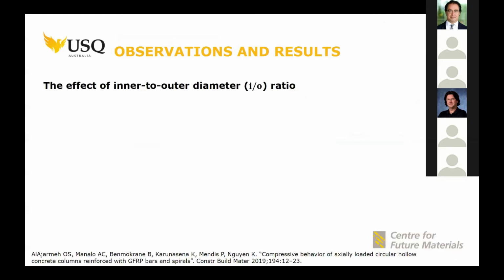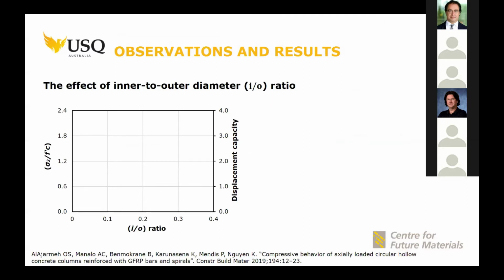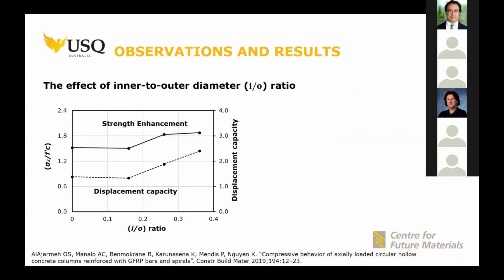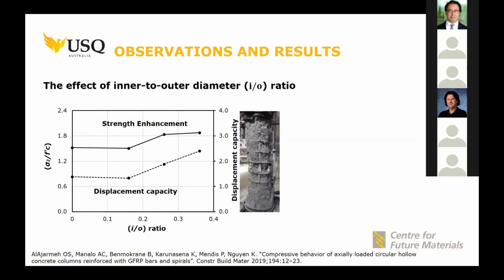We can tell from the test results that the effect of the inner to outer diameter ratio was very clear. And we were surprised to see that increasing the inner to outer diameter ratio increased the strength and increased the displacement capacity. That was absolutely related to the properties of the reinforcement, which steel reinforcement cannot do, because of the linear elastic behavior of these bars until failure. One interesting thing we saw with the maximum inner to outer diameter ratio column is its failure mode. You can see here that the failure was inside the concrete core with the longitudinal bars, but without any failure in the lateral reinforcement, which is different from all the previous columns. And we relied on that.